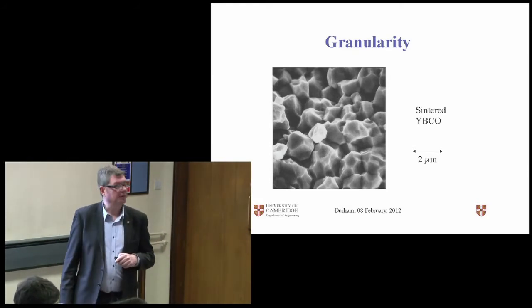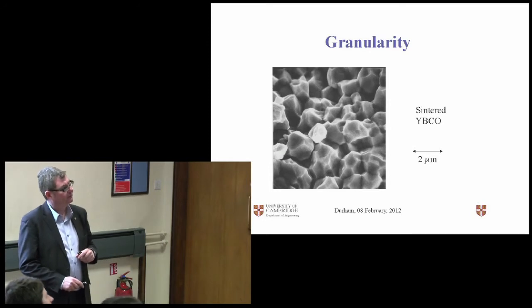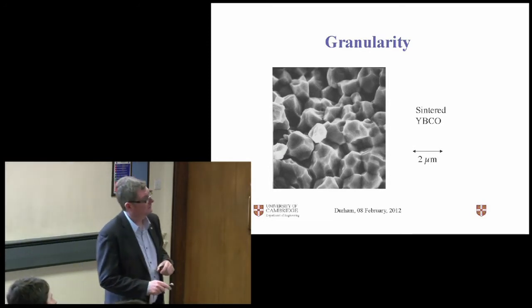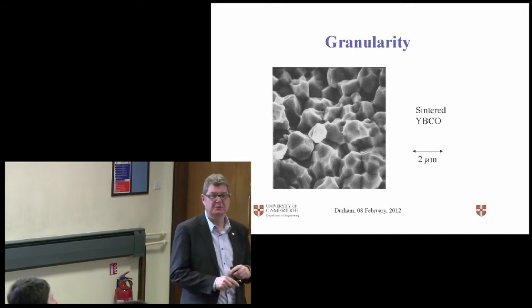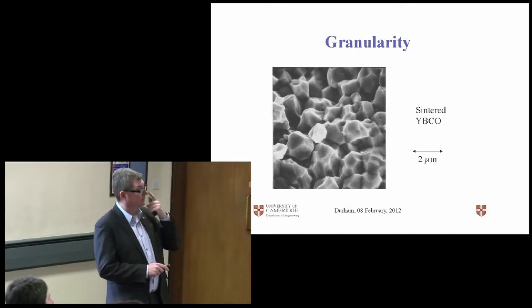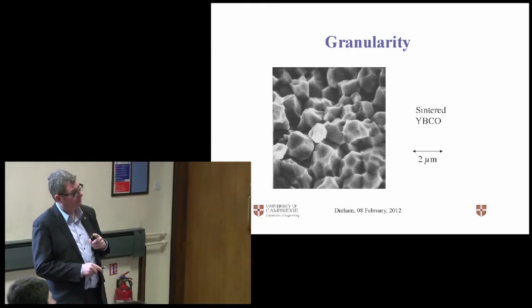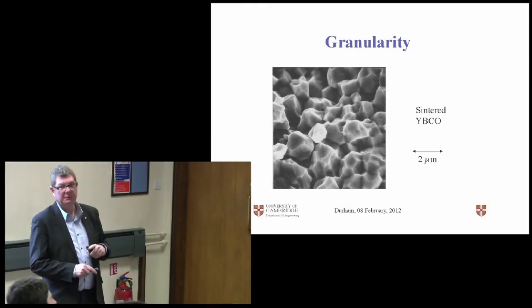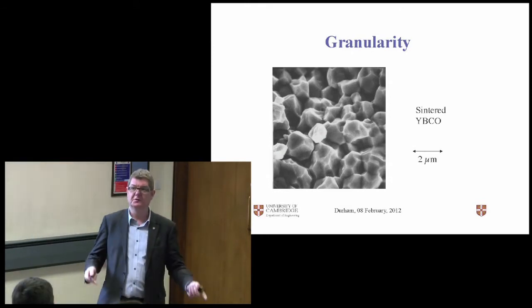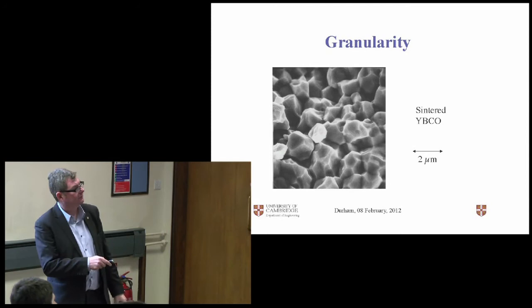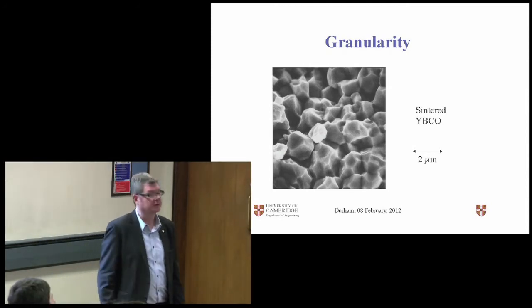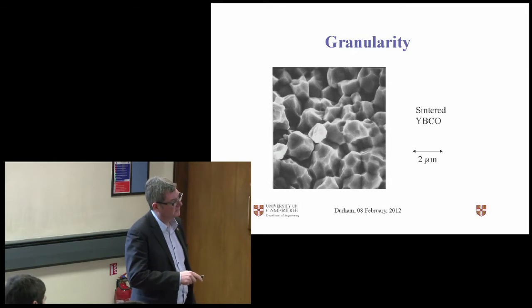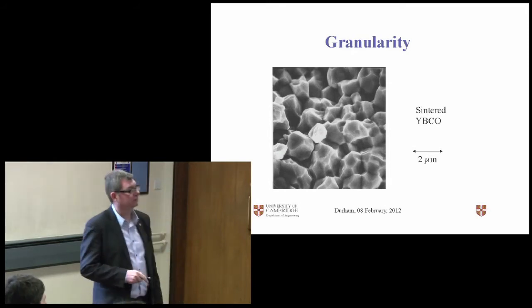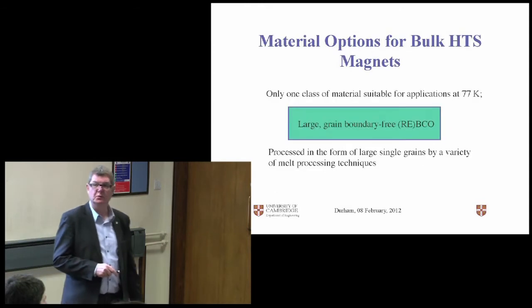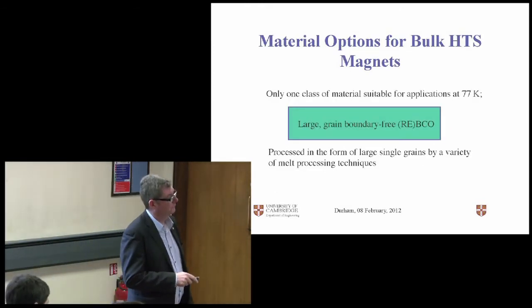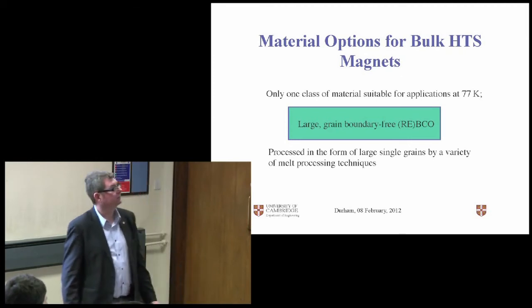Okay, so we take rare earth-bearing copper oxides, and we look at their microstructure. And I actually personally took this micrograph in 1987. It was one of the first YBCO samples I made when I worked at Plessey. And you can see that we've got this very granular structure. And the problem with YBCO, I said at the beginning, we want large currents on large length scales. These grain boundaries don't conduct current very well, they're insulating. So we don't get currents flowing over large length scales, we get very localized intragranular currents, and they give us very small trapped fields. So multigrain YBCO is no good.